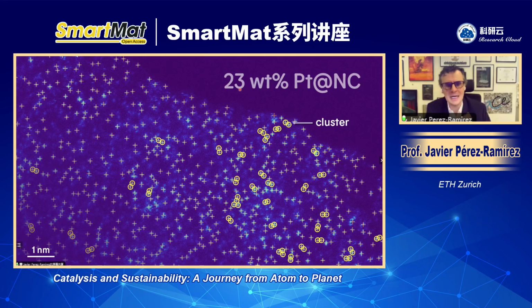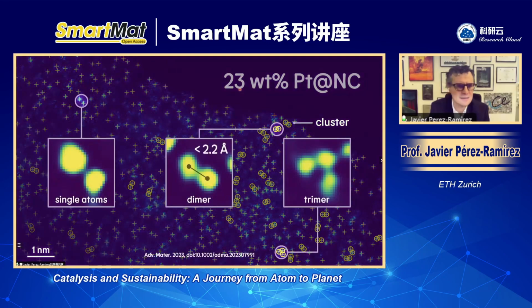And how do we know that these are clusters? Well, we know that these are clusters or single atoms because of the following. This is 2 single atoms, and this is what we call a dimer. And we know that this is a dimer because the distance between the 2 atoms is lower than the platinum-platinum bond distance.